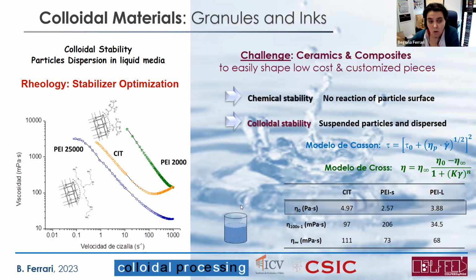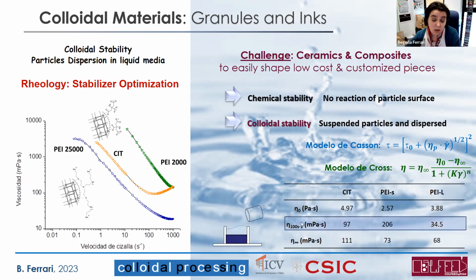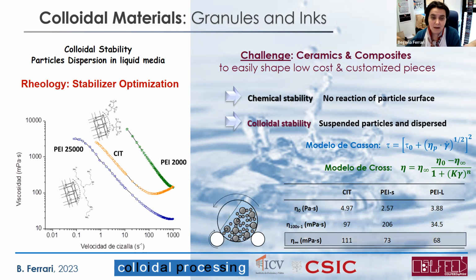For example, we need to know how is the viscosity at rest, because with that we have an idea if we can store the particles, avoiding settling or sedimentation of particles. We need to know what is the rheology in use, because with this number we can speculate on the possibility of shaping this ink. And also we need to know what is the rheology at infinite shear rate, because with that we have the idea how this suspension is going to react to a strong process like milling or spraying. So the rheology gives us an idea of all the parameters of the process that we need to know to shape an ink, to shape a material.